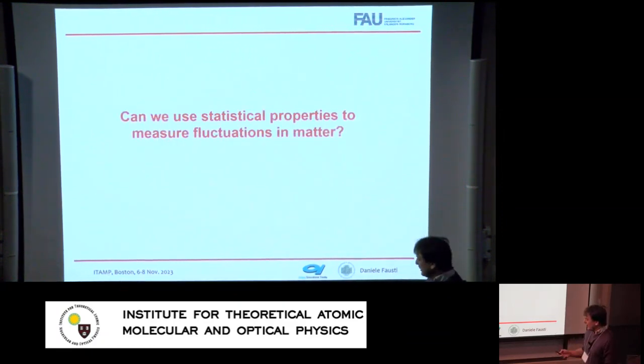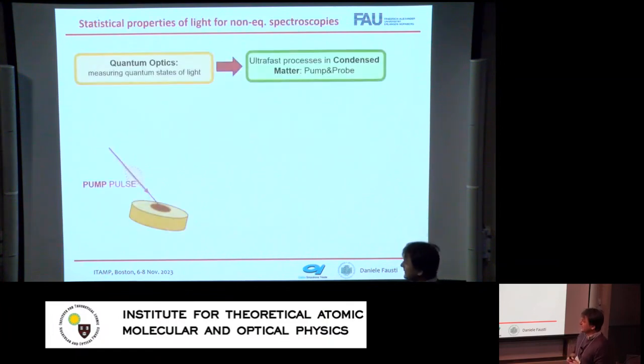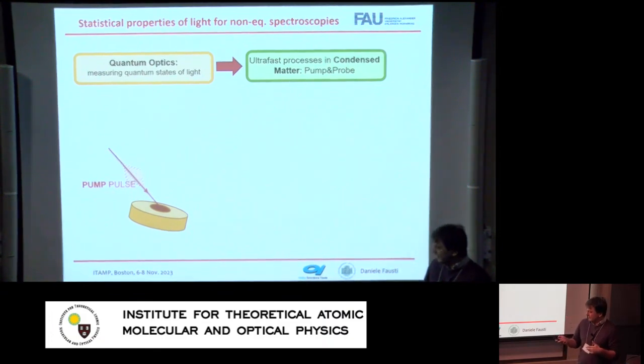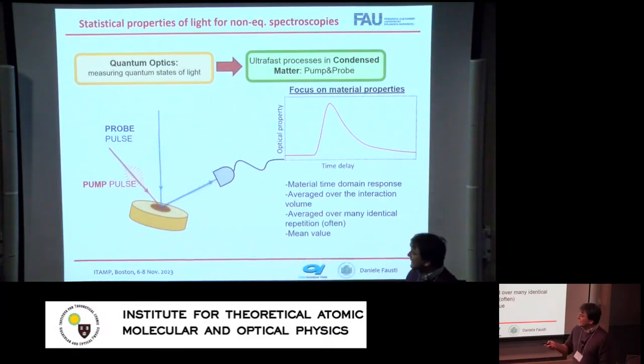So our idea was, if I want to dynamically measure the fluctuations of some relevant degrees of freedom in matter, I should try to define an observable which allows me to measure these fluctuations. And of course the observable depends on the specifics of the problem, but the general philosophy that we have tried to follow over the years is the following. Whenever I do a dynamical experiment, I usually focus on studying the property of the material, and light is used on one hand to perturb the material, and on the other hand to measure the material response. This is just an obvious pump and probe experiment for this graph.